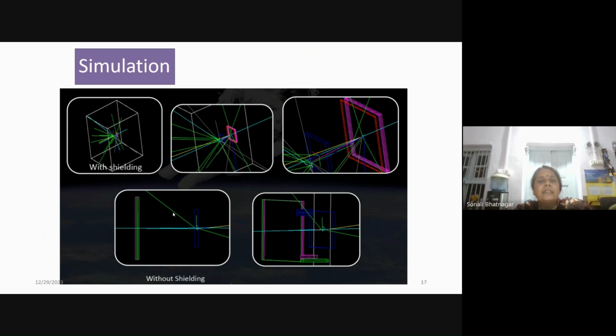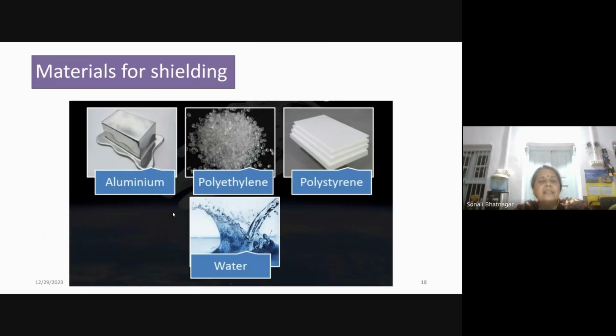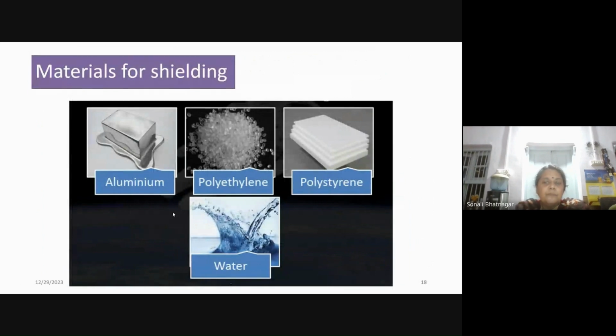So the simulation was again done in Geant4, where one was without shielding and the other was with shielding. And in this, we had taken these materials: aluminum, polyethylene, polystyrene, and water. And polystyrene is the organic scintillator that we have been using in the lab. So we were more interested in this part. So these are the ROOT plots of the simulation which the student had done. And there are two plots that I'm showing you.